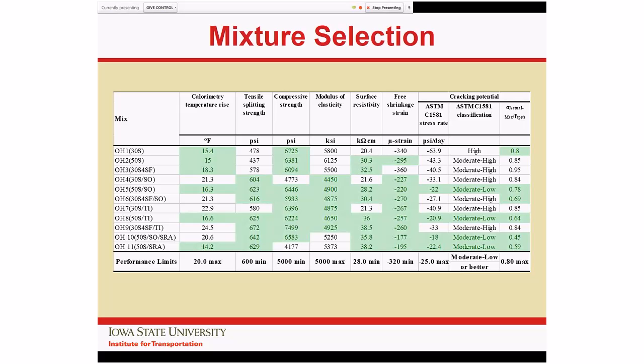And by basically coloring in all the cells that pass these somewhat arbitrary but reasonable pass-fail parameters, we basically whittled it down to two different systems that seem to provide the best bang for the buck. Now, again, any one of these would probably be acceptable, but I was going for an optimum. And in these cases, the two that worked really well were the systems with 50% slag, no silica fume, and